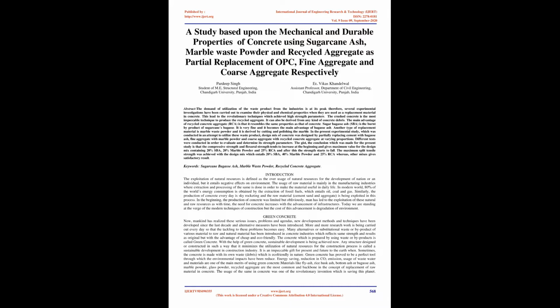The conclusion of the present study is that the compressive strength and flexural strength tend to increase at the beginning and give the maximum value for the design mix containing 20% SBA, 20% marble powder and 25% RCA, and after this the strength starts to fall. The maximum split tensile strength was achieved with the design mix which entails 20% SBA, 40% marble powder and 25% RCA, whereas other mixes give satisfactory results.